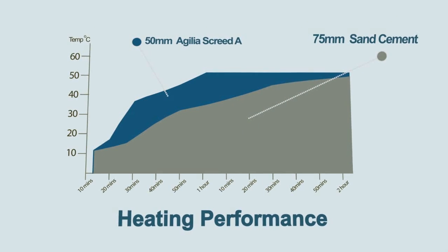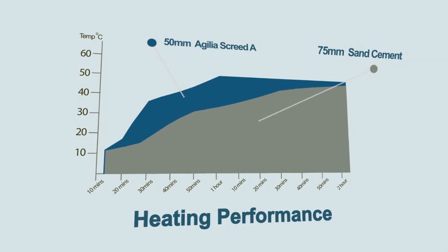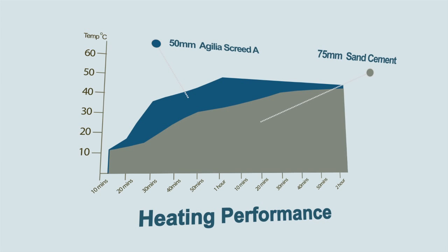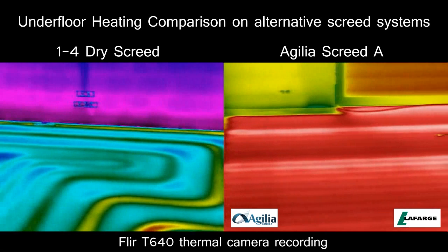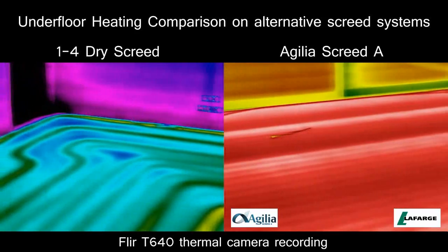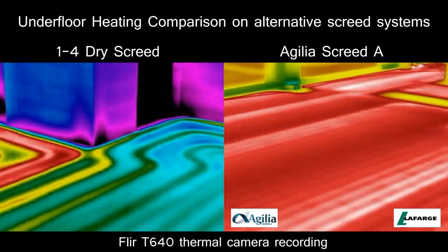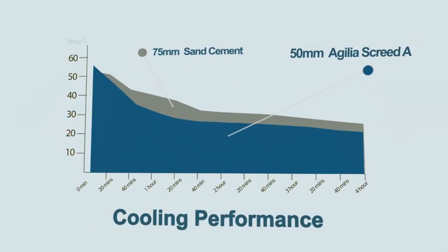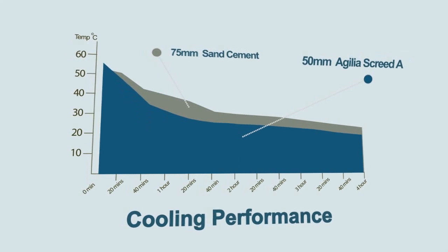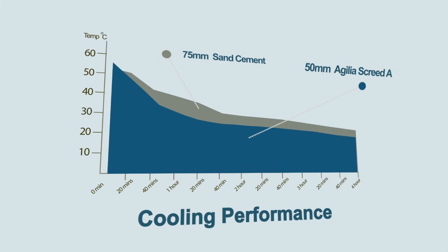Tests have proven that due to the increased thermal conductivity of Agilia Screed A, its greatly improved compaction and density compared to sand cement screeds, the surface temperature of Agilia Screed A reacts more quickly and efficiently to heat input. When the underfloor heating is switched off, despite being laid thinner than other screeds, the Agilia Screed A retains heat for a comparable amount of time. Combine this with the heat-up performance, and Agilia Screed A is the first choice for use with underfloor heating.